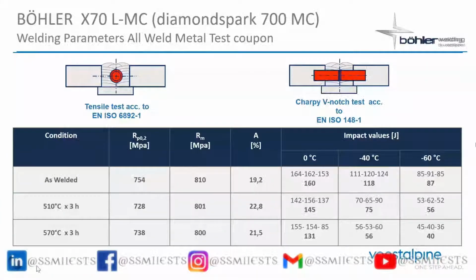Consistently, the yield was above 700, let's say 725 megapascals, and UTS of more than 800 megapascals, as well as impacts right down to minus 60 degrees centigrade. Next.